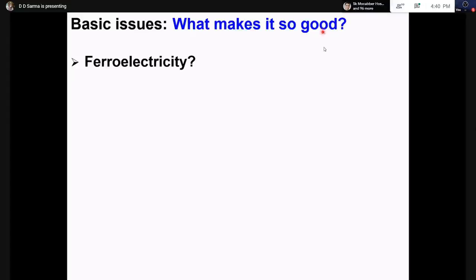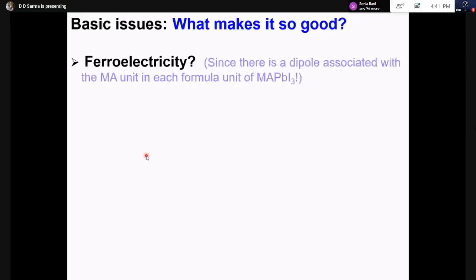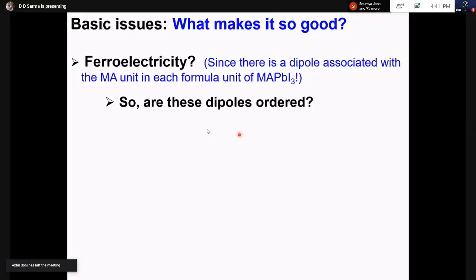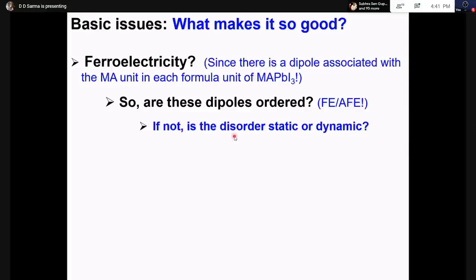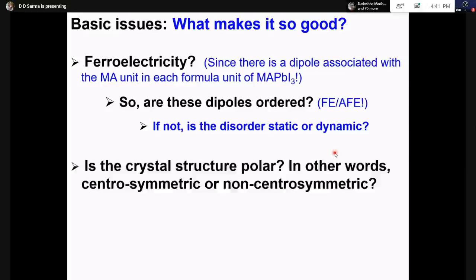So that's why it's very important to understand whether the system is polar or not. So we come back to that same question, what makes this material so good? Is it ferroelectricity, in addition to the properties that we understand, because there is a dipole associated with the MA unit? So the question that we are really asking is, are the dipoles ordered? They don't have to be ordered. If they're ordered, they can be ferroelectrically ordered or anti-ferroelectrically ordered. Or it can be disordered, and if it is disordered, it can be static, like in a glassy state, or dynamic, as in a paraelectric state.